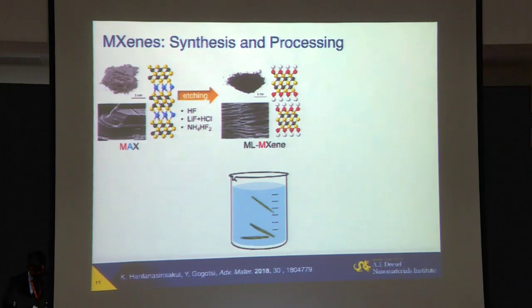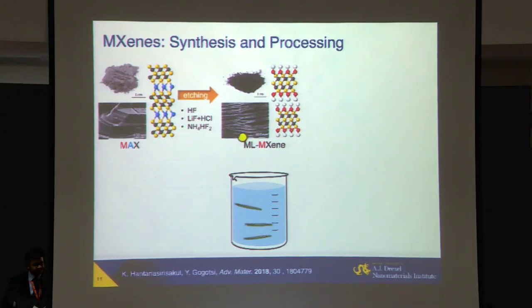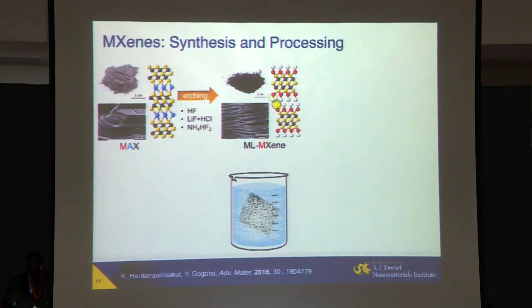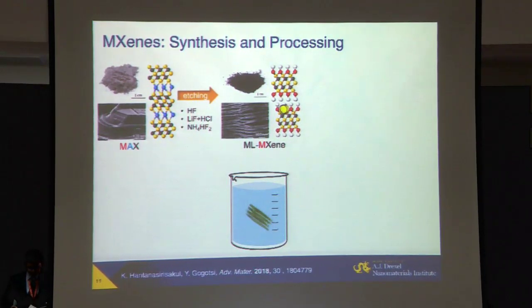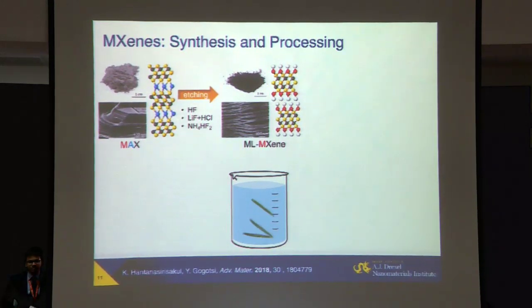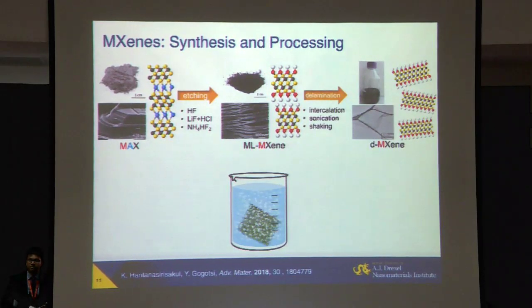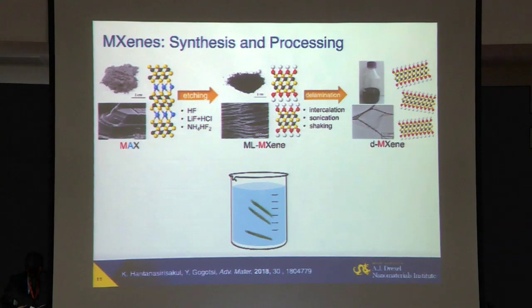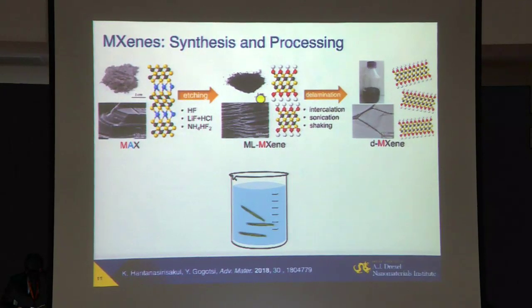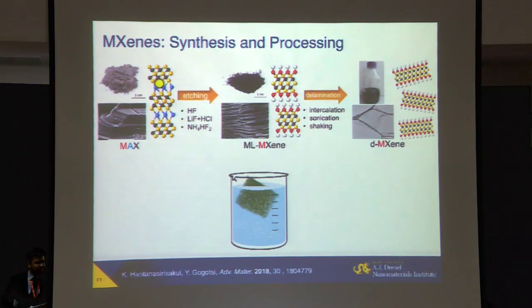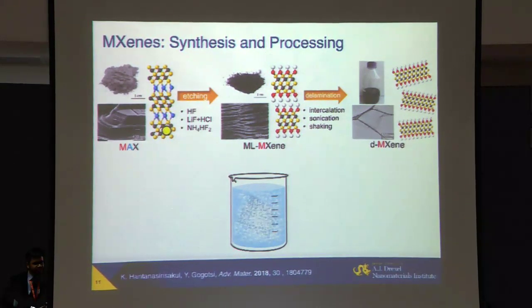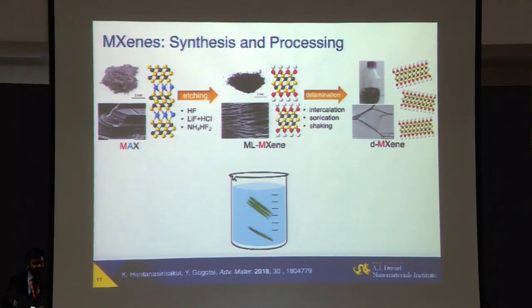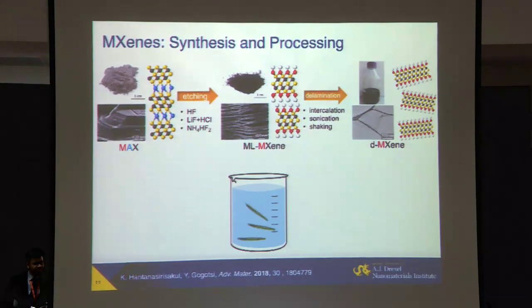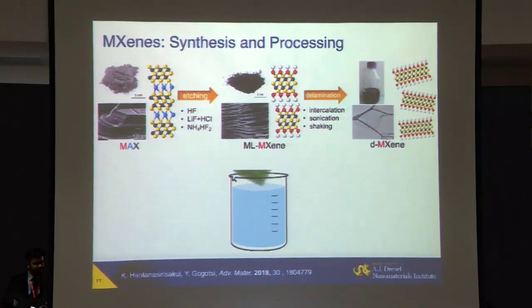What we have now, we have MXene layers, which are still bonded to each other. You see, this picture looks like a thermally exfoliated graphite or vermiculite clay. But now they're bonded by weak hydrogen bonds because there are OH or oxygen or fluorine groups on the surface. So we can disperse them just the same way we disperse graphene oxide, clay, or other materials because now there is weak bonding. One important thing is here. You cannot really easily mechanically exfoliate those materials because those are not van der Waals, they're strong covalent, metallic bonds, depending on what kind of element is used, so we have to etch them.